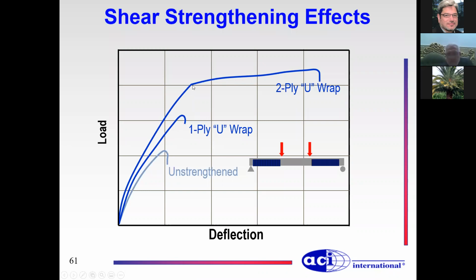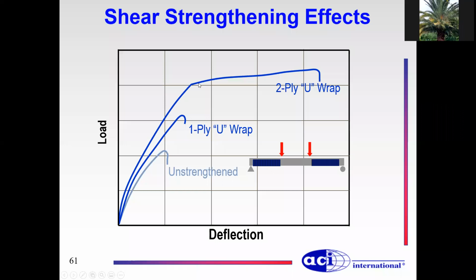If I use more of FRP, let's say 2 plies of U-wraps in here, I'm going to change the failure completely. I'm going to avoid shear failure and force the failure to go in flexure. And usually this is the type of failure that we prefer to have in our concrete systems, because flexural failure is ductile. It has got an area under the curve in terms of energy absorption, much better than what you get with shear failure.